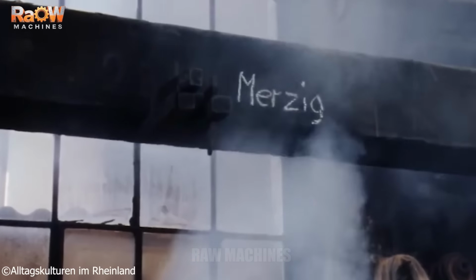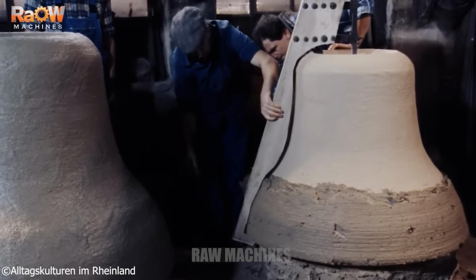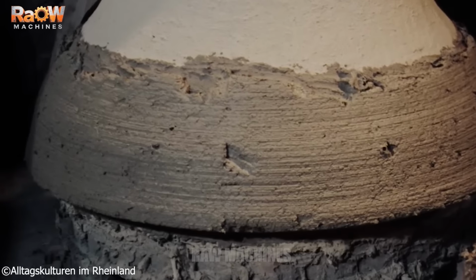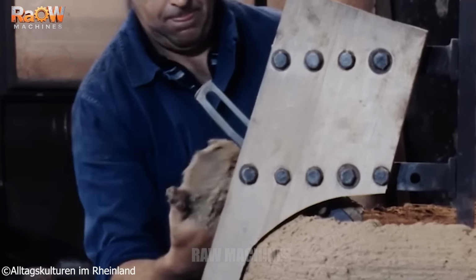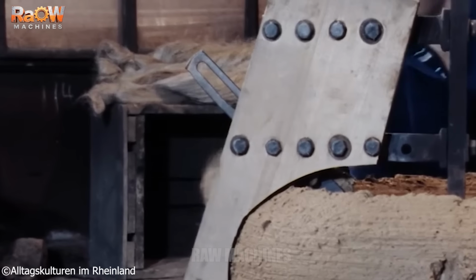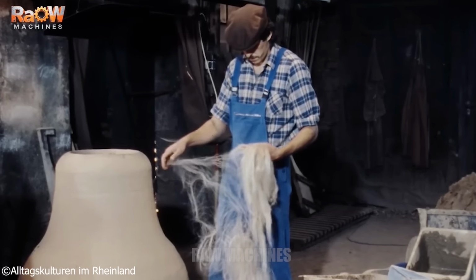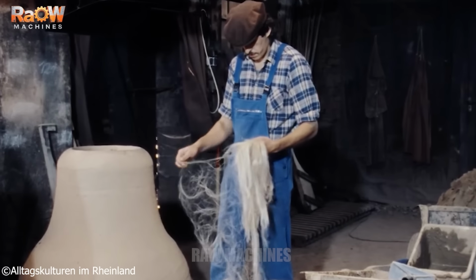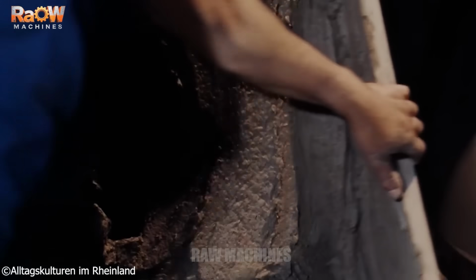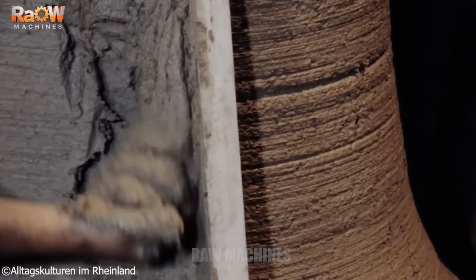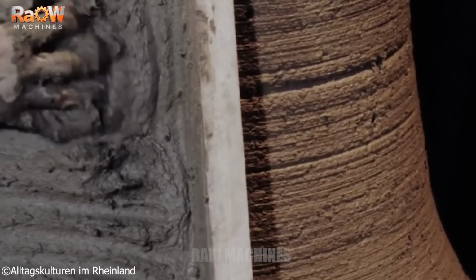After approximately 25 days, once the fine layers have stabilized, the outer mold is reinforced with stronger clay mixed with calf hair to increase mechanical strength. From this point onward, heat drying begins. The core is fired with charcoal briquettes and coke, causing the wax to melt away and leave negative impressions on the inner surface of the mold.